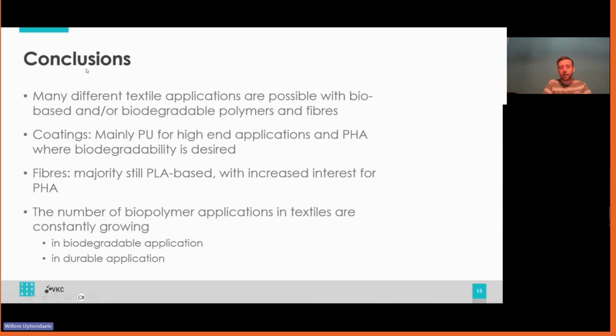So to conclude, there are quite a lot of different textile applications possible with novel bio-based and biodegradable materials. For coatings, we are looking at mainly polyurethanes when we think of high-end applications, and PHAs where we think of applications where biodegradability is desired, for example, the prints on clothing. When it comes to fibers, the majority of the developments is still based on PLA. There is an increasing interest for PHA, but the melt strength of PHA is quite low, which makes it quite difficult to spin PHA-based fibers at the moment.